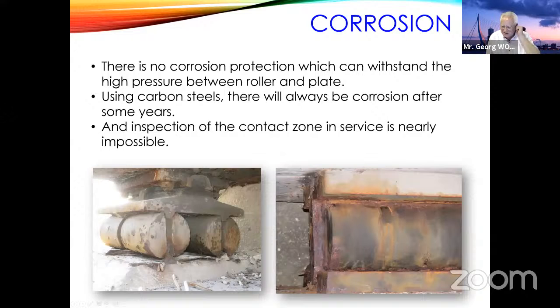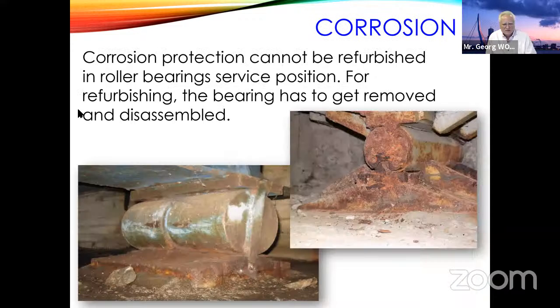So you see, these are the examples for the corrosion. Especially in many cases, we found a lot of corrosion at the contact lines, which is difficult to see from outside. And it looked not so bad from far away, but in the details you will see that the bearings are not able to move anymore. The inspection of this contact zone is very difficult. I think everyone who is checking bridges has already seen a lot of such examples in his job.